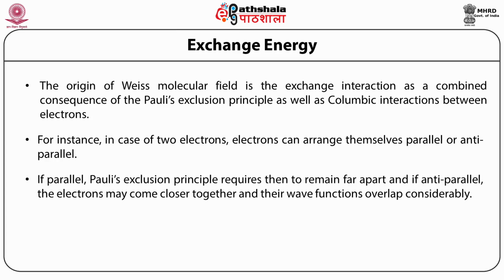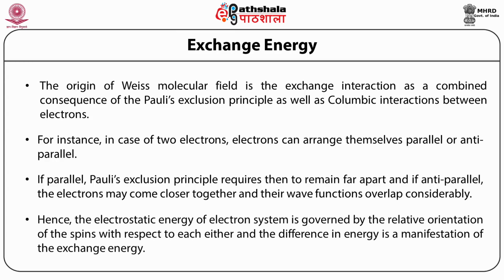If parallel, Pauli's exclusion principle requires them to remain far apart, and if anti-parallel, the electrons may come closer together and their wave functions overlap considerably. Hence, the electrostatic energy of the electron system is governed by the relative orientation of the spins with respect to each other, and the difference in the energy is a manifestation of the exchange energy.